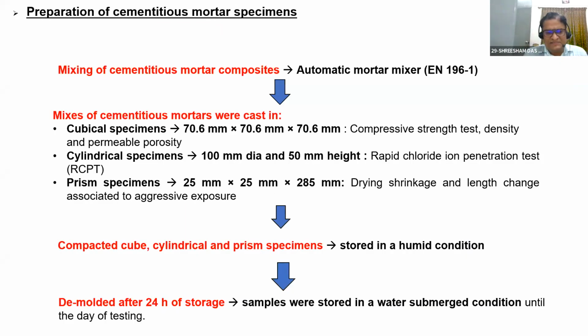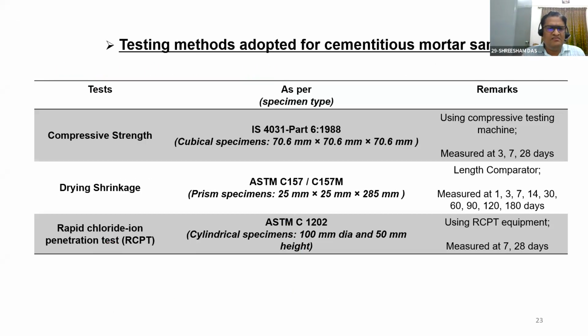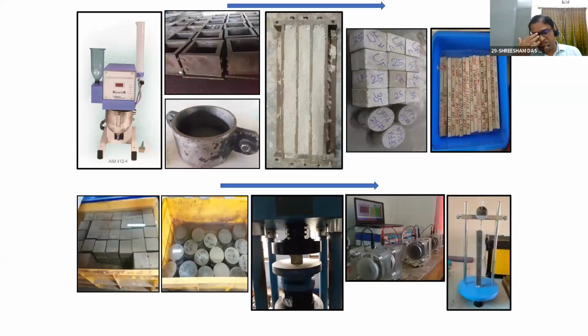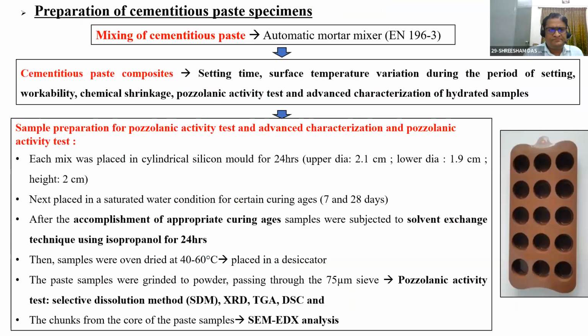All the specimens were mixed and cast for standard testing methods: cubical specimens, cylindrical specimens for the RCPT test, and prism specimens for the drying shrinkage. These are the standards for compressive strength, drying shrinkage, and RCPT, and the tests were made by following these standards. So these are the specimens. You can see the mortar mixer, then the specimens, and all the testing methods presented here.